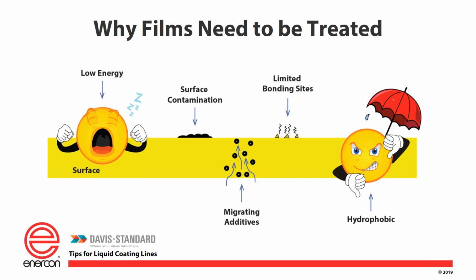Now, why is that? Well, just a couple of reasons. Number one is it's simply a low energy surface to start with, meaning there's no polarity on that surface. It's just a very neutral surface. But then we have other problems, right? We have surface contamination that might be as a result of migrating additives, slip additives, anti-blocks, possibly colors, whatever it is. Maybe it's a post-consumer product. There's 30% recycled material in there, and within the scope of that, there were some additives within those categories that now are sitting on the surface, which limits the surface's ability to bond and limits its ability to wet the liquid. So the surface treaters, corona treaters or flame treaters, are there to correct for all these issues.